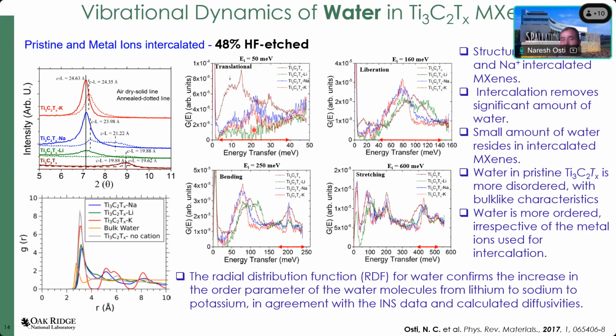It means that once you intercalate the metal ion between the layers, it removes a significant amount of water from the MXene material. Now, if you look at the intramolecular vibrational modes, for example a bending mode and a stretching mode, you can see that in the pristine MXene the peak is very broad. Once you intercalate the metal ion, the peak becomes much narrower. It means that the water molecules become much more ordered once you have the metal ion intercalation. And that order parameter goes up depending upon the size of the ions, which is well reflected by the radial distribution function calculated from the MD simulation.